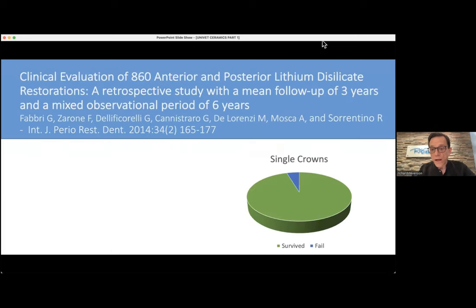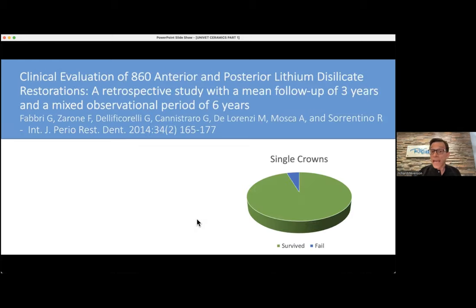The numbers for Emax bridges were ridiculously, dangerously low. When this paper came out I said: Dr. Sailer's separate paper is saying something even worse — I am no longer going to recommend Emax as a bridge material. Much to Ivoclar's disappointment, I said I can't recommend it. Emax has found its place: single unit dentistry — veneers, inlays, and onlays. That's it. For bridges we had to look at other areas, and at that time we were still doing PFM. When we look at single crowns for Emax — whether on an implant or natural tooth, monolithic or bilayered — survival rates are absolutely acceptable. So the data converged very powerfully to tell dentists: if you're going to do a bridge and want it to look beautiful, it'll have to be a PFM if you want it to last. If you're okay with about a 30% failure rate at 10 years, you could do Emax — but that's not a number most of us could tolerate.